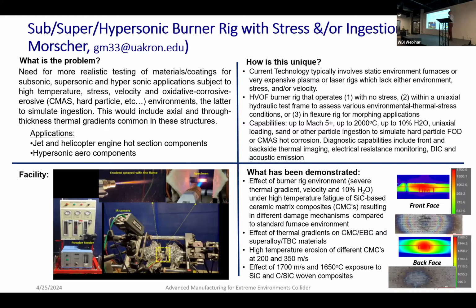We can vary the water content somewhat by the gas composition, so we get up to about 10% water vapor. It's not like a real engine, but it's better than just a regular air test. And again, we have quite a bit of diagnostic capability. We have cameras on the front and back, and a pyrometer. We can do electrical resistance in situ to monitor health during the test.